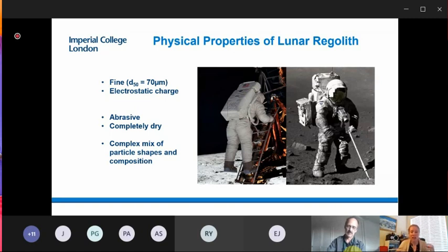And it was by and large collected in an ad hoc way by the astronauts as they moved around the moon. But what we do know is that it's very fine. It has a mean particle size, average particle size of around 70 microns. It's incredibly electrostatically charged, and this is because of the lack of atmosphere and the lack of water. So it carries a high electrostatic charge. In terms of quantity, we don't really know that much about it, but we do know that it sticks to things. It's incredibly abrasive. It is completely dry, and it's a really complex mix of particle shapes and composition.